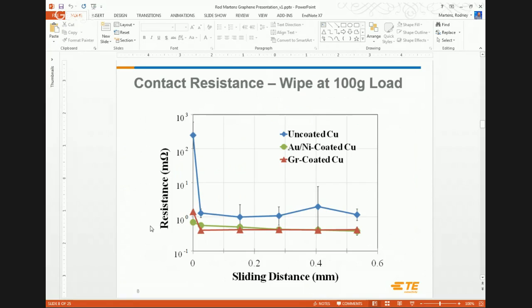Once we're at full load, on the same curves, we introduced a little bit of wipe or translation at the contact interface. Now this would simulate when you plug or unplug a connector. You're displacing some oxides, corrosion, whatever may be on the contact. And you can see in all cases, a little bit of wipe helped quite a bit. In fact, the blue one, we were able to displace that oxide and get it down similar to the controls that are shown here with the red and the blue. I'm sorry, the red and the green.